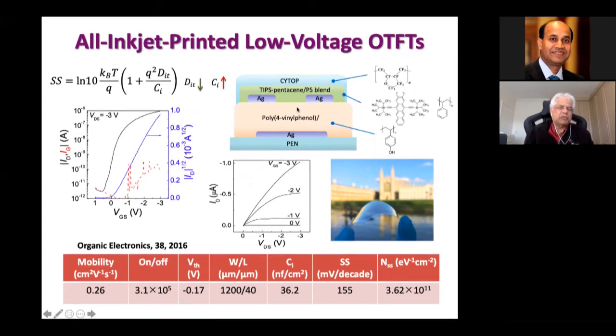And if you look at the silicon MOSFET, thank God the insulator was silicon dioxide. Silicon dioxide forms a perfect marriage in the sense that the interface state density can be really super low. It tends to be about 10 to the 10 or less. So this is an order higher than that. What I'm trying to show is that interface state density becomes a very important parameter, whether you make a sensor out of printed transistors or a sensor interface out of it. To get low voltage operation, you need to bring down interface state densities.